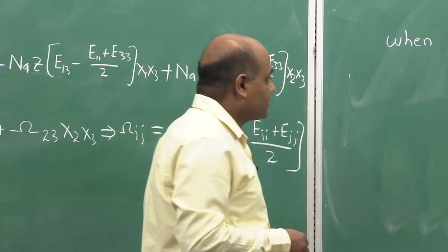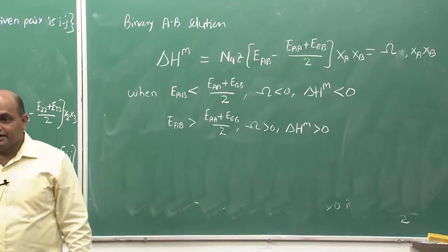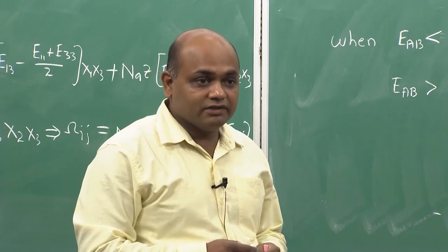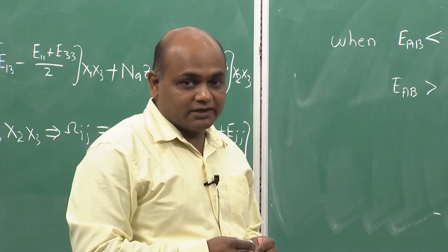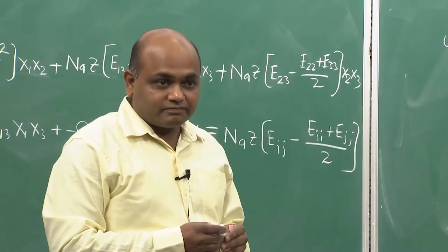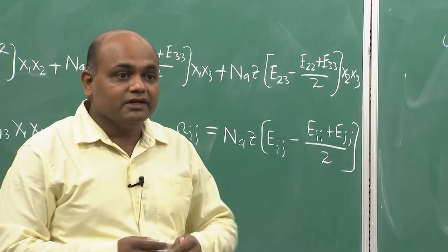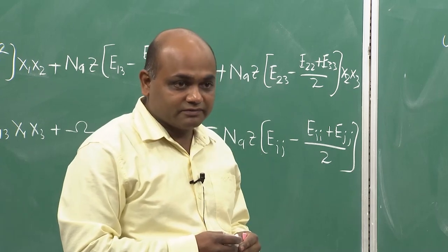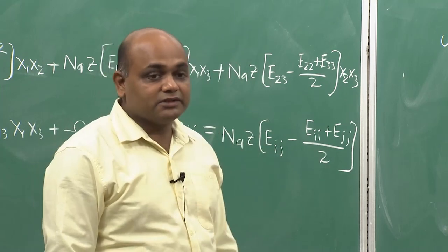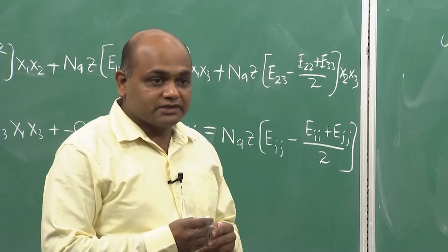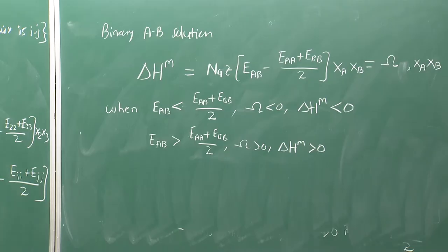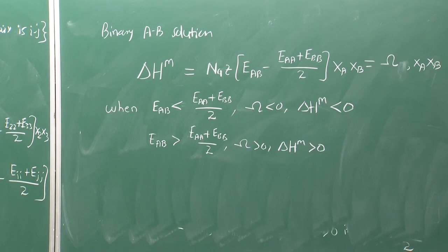Okay. So this is important. We went over this model in a little bit of detail because it is important to understand how the interactions between the atoms give rise to changes in the Gibbs free energy, basically changes in the enthalpies and entropies, because they also affect diffusion, especially the cross effects. Because of these different interactions, the atom jumps will be biased in a multi-component system. And so it is important to understand how these atom interactions affect the Gibbs free energy changes.